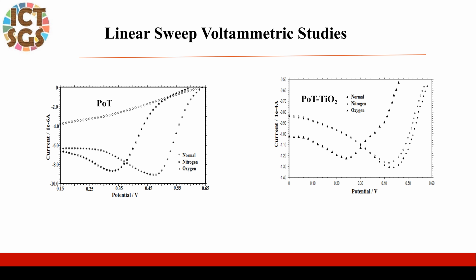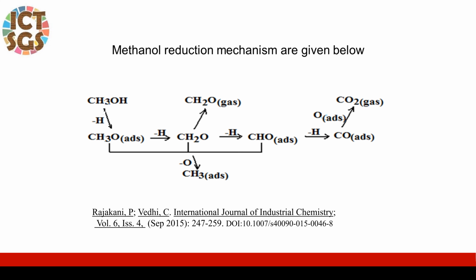Linear sweep voltammetric studies have been recorded in the presence of acidic methanol. The ORR activity is enhanced by nitrogen saturated buffer for PoT, but the oxygen saturated buffer only enhanced the ORR activity for PoT-TiO2. The methanol reduction mechanism is shown here.